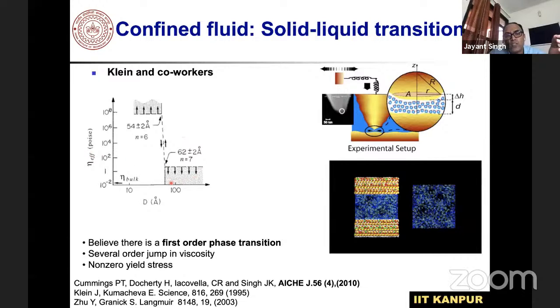If the viscosity jumps by many fold, then this is indicative of a phase transition from a very large gap D, which is the gap between the tip of the AFM and the surface of the substrate on which the fluid is kept. If you bring it closer, then there's a viscosity jump indicative of an ordered system, that is indicative of a solidification.